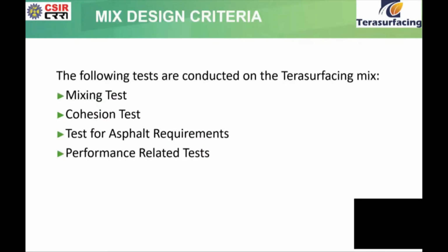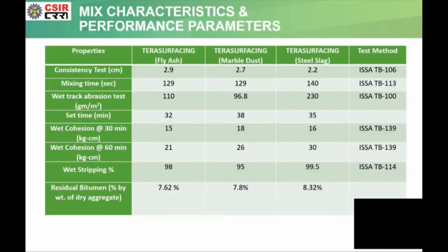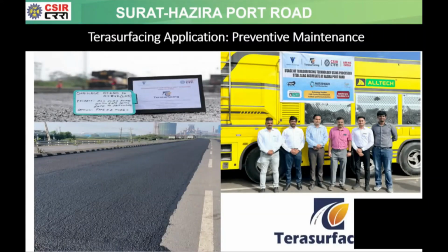These are the different tests which are required to be done in order to carry out the mix design, which comprise mixing test, cohesion test, test for asphalt requirement and all. So it's a typical technical mix design methodology which we need to follow. This is the mix design parameter which has to be achieved while carrying out the Terasurfacing with 3 different types of industrial material, whether it is fly ash, marble dust or steel slag. If you have any of these materials available nearby, you can adopt this technology in place of natural aggregate, and we can construct the road using it.